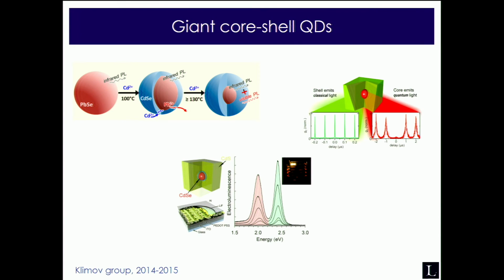Let me now move to the last part, which is connected to quantum dots, the so-called giant quantum dots or dot-in-bulk systems. The inspiration came from the work of Professor Klimov, who first proposed these materials in which you have a quantum confined system in the core of your structure, surrounded by a pretty thick shell. The thick shell has a classical behavior from the optical point of view, while the core is still a quantum system.